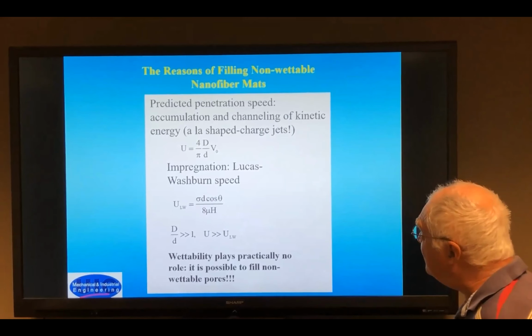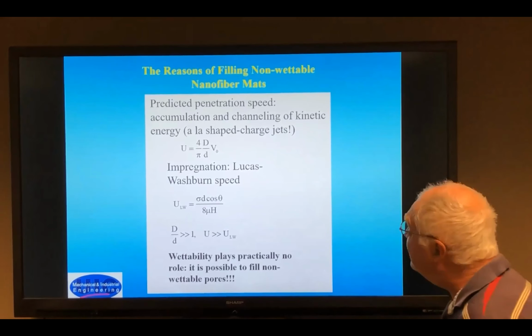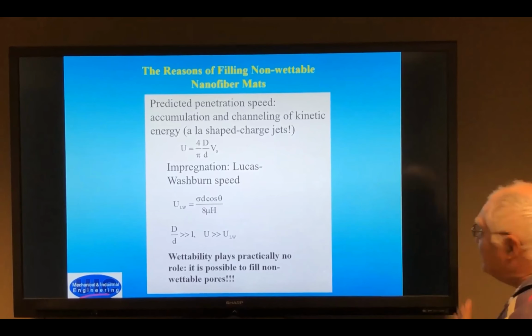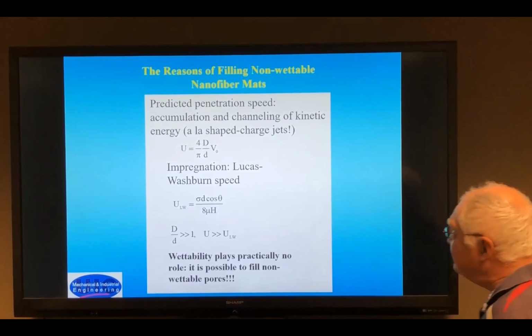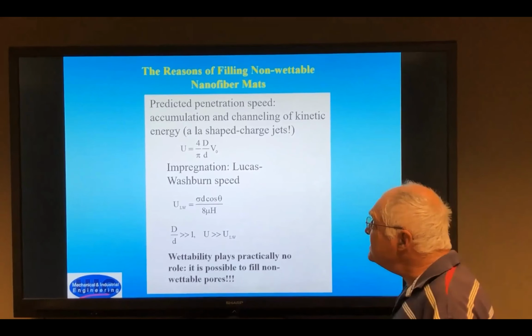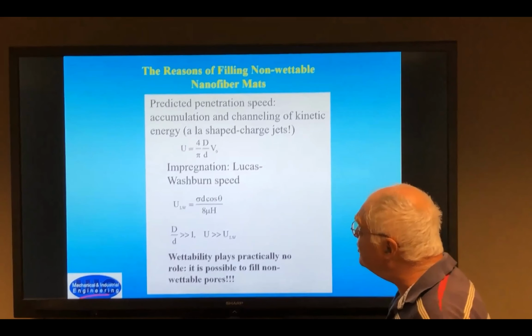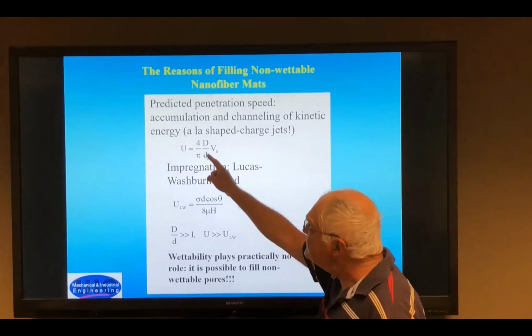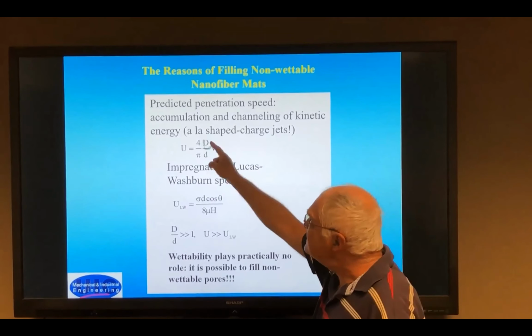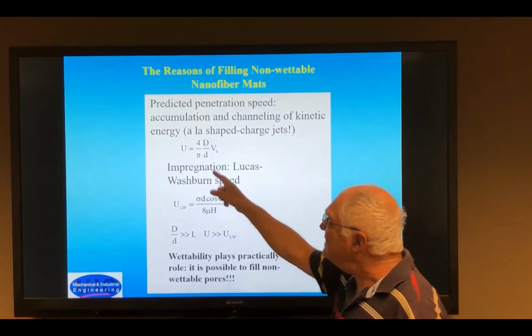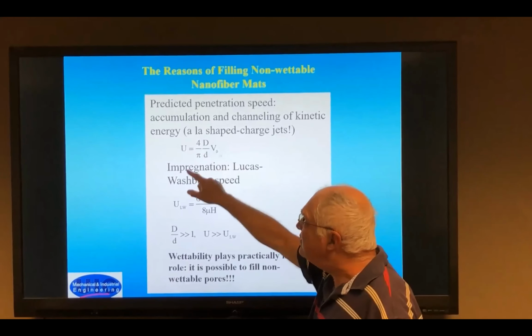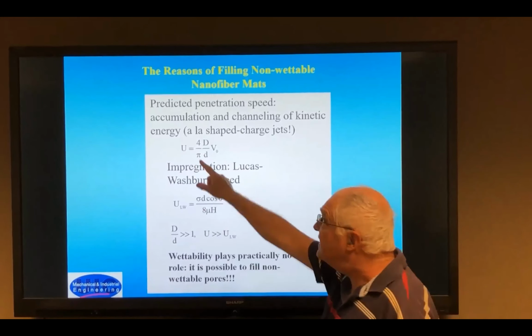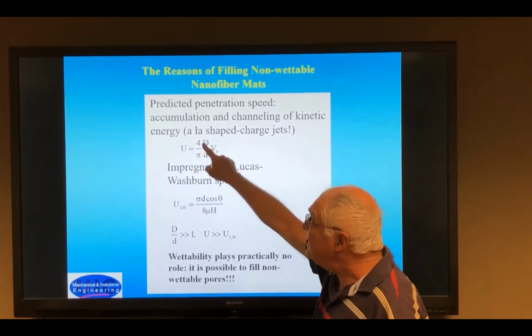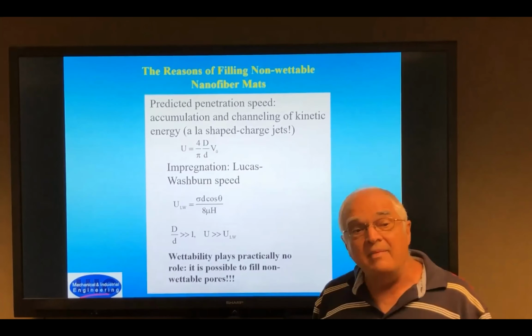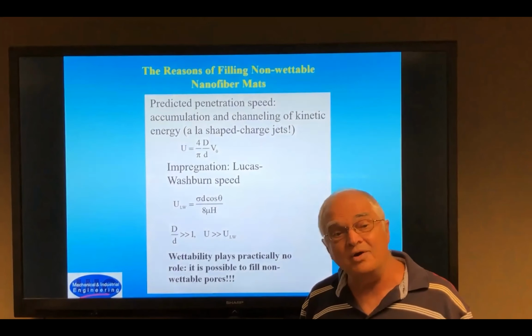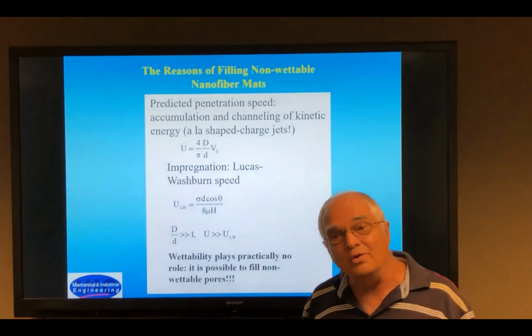Now the reason for this failing waterproofness is the so-called hydrodynamic focusing effect, which we once discovered. Essentially, when a water droplet impacts a pore of size d, and the droplet size is capital D, with velocity v0, then the penetration velocity is given by this u. The ratio of capital D to small d, if the pores are small, might be on the scale of 100 or even 1000.